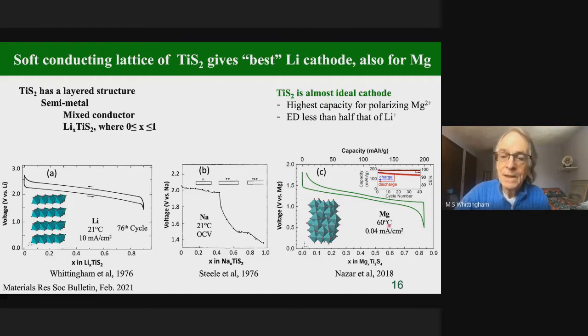So you can see the voltage here for magnesium is almost a volt less than for lithium. So in the end, a magnesium battery has only about half the energy density of a lithium battery. So magnesium batteries are not really viable, even though there's been lots of talk about them. Calcium might be more interesting, if we can get calcium to work, because the calcium voltage will be closer to that of lithium. Let me show you why we only have lithium-ion batteries today.